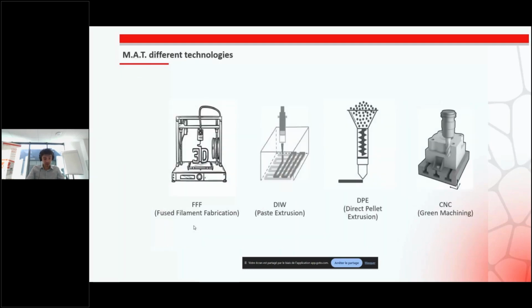The M.A.T. can use an FFF head, so a filament goes through a nozzle and you can print parts. Or a direct ink writing head, which is a paste extrusion system. Or direct pellet extrusion, where the material is not a filament, not a paste, it is the same pellet used for ceramic injection molding, for instance. And on top of that, the machine can use a CNC head to do machining to improve the surface aspect of the parts after printing.